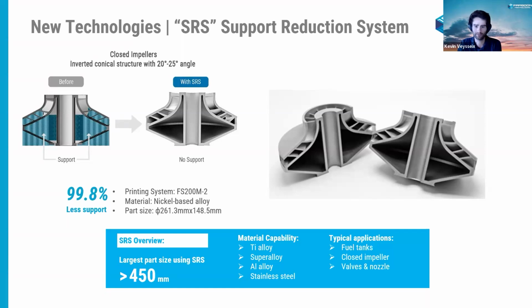So this is theory on the left, that's software, but on the right side you can see the part. And the part was rebuilt this way, we cut it afterwards, and the only support we needed was here on the angles, because this would have been floating otherwise. It's not even hovering, it's in the air. We have parameters for titanium, for nickel base alloy, for aluminum and stainless steel. And we have printed parts that are bigger than 450 millimeters already with this application. So it's not magic, it's not a button you click and there is no support, it works perfectly, but it can really help you in such cases.